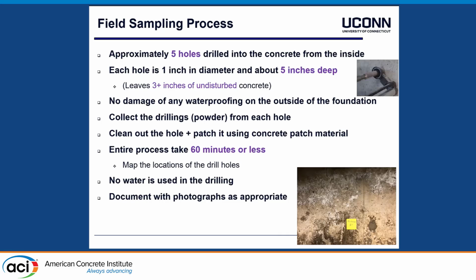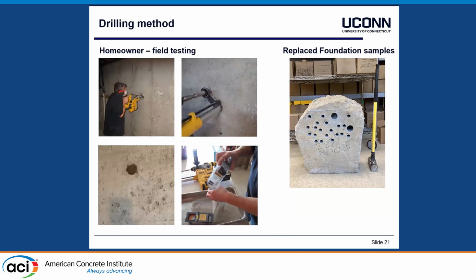We can drill more holes. It's not a problem. We can analyze more just based on statistical variation and analysis. We have found that 5 holes is sufficient for those homeowners to evaluate the presence of pyrrhotite or not. With those foundation samples you see here, we can use those to drill several times. Those are the 1 inch diameter holes you see here, and then we can analyze statistical variations within 1 sample and so on. And this is how it looks in the field.